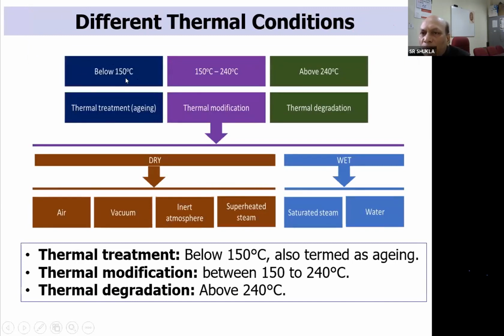Depending upon the range of temperature to which bamboo is going to be exposed, these thermal processes are defined with different names. When temperature is below 150 degrees centigrade, it is also called aging. So below 150 degrees centigrade is the thermal treatment. When temperature is in the range of 150 to 240 degrees centigrade, that is called the thermal modification. Here the chemicals present in the bamboo are going to be modified. They will be converted into other chemicals, and that will provide improved properties to the bamboo. And above 240 degrees centigrade is not good for bamboo. The bamboo starts degrading, and that is why it is called the thermal degradation. So there are three different thermal treatment conditions: thermal treatment below 150, thermal modification between 150 to 240, and thermal degradation above 240.